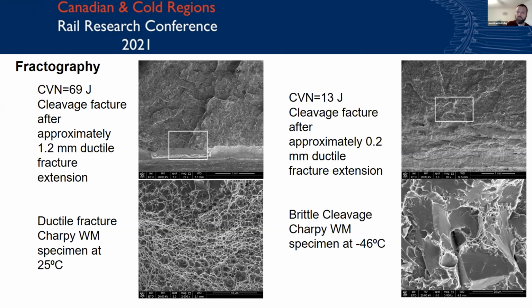So between the extreme ranges that you might expect this material to perform in, there is a vast difference in how it may actually perform in practice. When you look at the lower images, you can see that there are ductile voids forming at 25 degrees Celsius versus a completely different brittle fracture surface at negative 46 degrees Celsius.